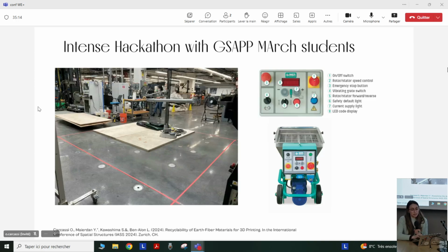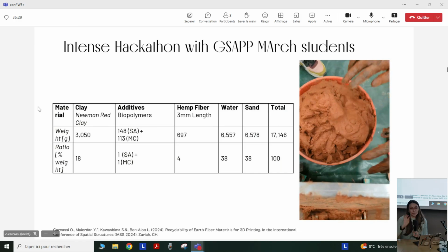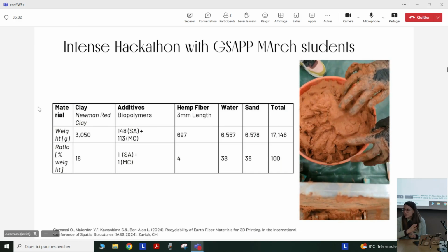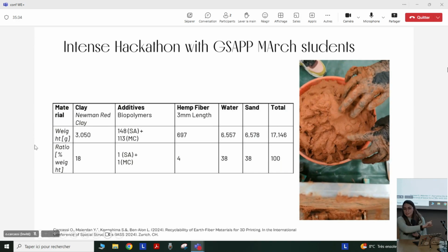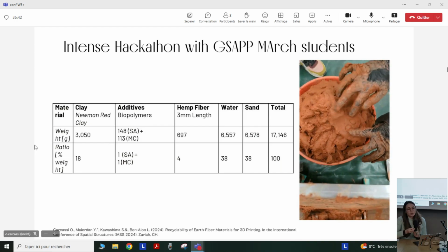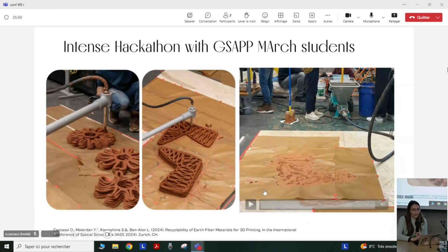So we really had to work with these big machines, which is called SCARA from 3D Potter, and this pumping system that for us was the enemy, because each pumping system has a limitation in terms of aggregates that you can use to 3D print. So instead of the 13% that we developed for the printing system in terms of fiber content, with this pumping system, we were only able to have 4% of fiber content in terms of mass. Still, you really see that the limitations are in the technical solutions.